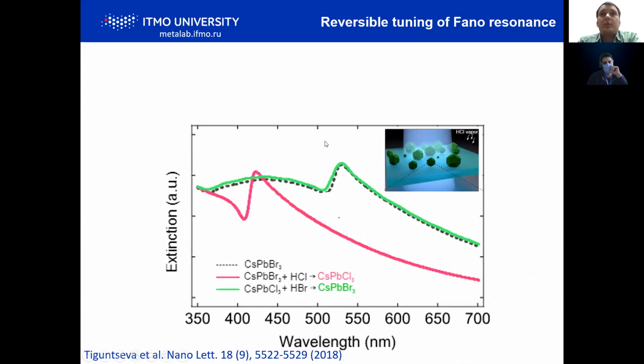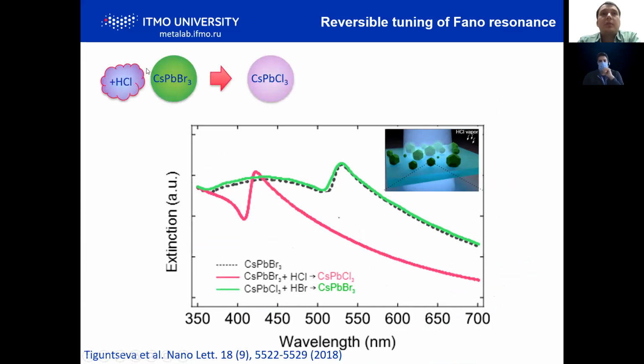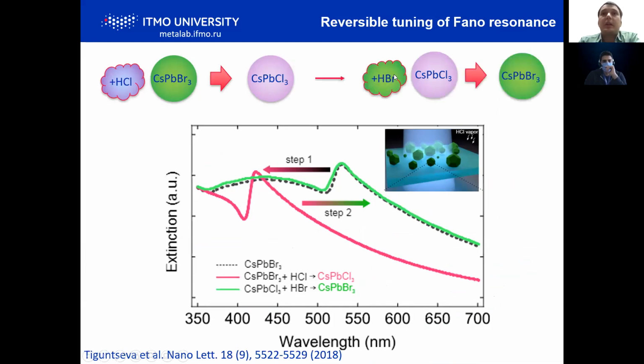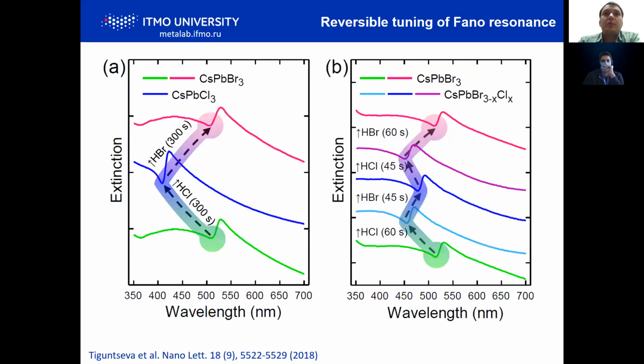And the question is whether this Fano resonance tuning is reversible. And the answer is yes. If we take bromide perovskite particles, expose them, make them chlorine, and then after this step, use exactly the same substrate with nanoparticles and expose it again to HBr acid, after that we can recover these nanoparticles and come back to the same state. This is true not only for complete bromination or chlorination, but also for some intermediate states. So this is quite a powerful technique for chemical tuning of nanophotonic designs.